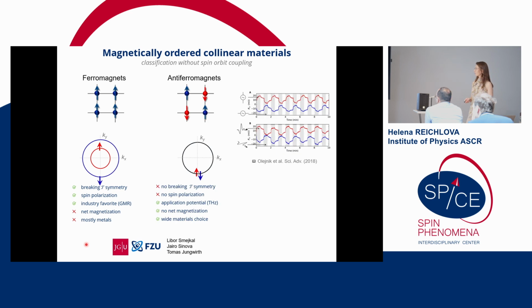At the same time, the antiferromagnets have many disadvantages in the sense that in the collinear case, they do not break the time reversal symmetry in the K-space because the spin bands up and down are degenerate. However, they have potential for very fast intrinsic frequencies. And also, as I said, there are more materials available, and in the context of neuromorphic computing, the antiferromagnets show the ability to have multiple stable states, which is very much desired. So there is also a lot of potential for antiferromagnets, but this absence of robust spin polarization is a clear disadvantage.